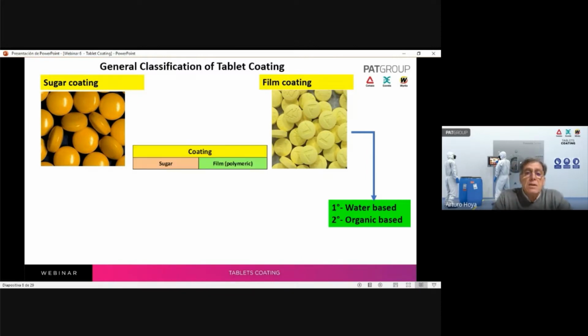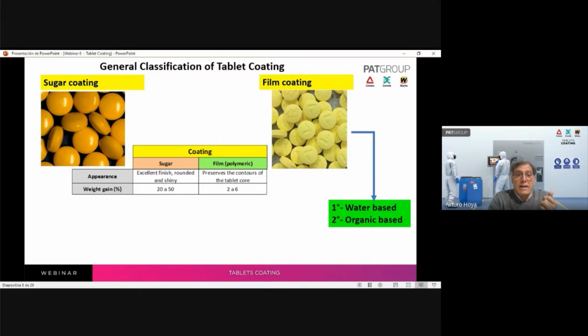Well, in comparison between them. So, appearance, you have that the tablet coating with sugar have an excellent finish, rounded and shiny, and the tablet with film coating preserve the contours of the tablet core. The weight gain in the case of sugar, you have a very high levels of weight gain, 20 to 50, and in the case of film polymeric, is 2 to 6, is very small.